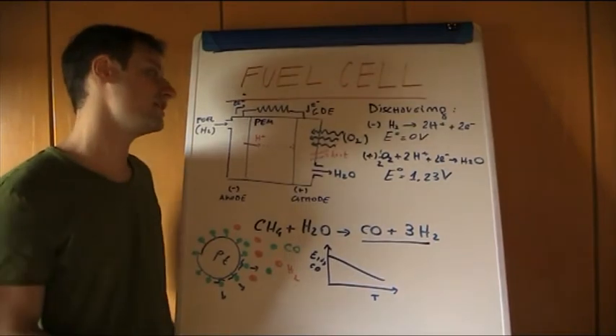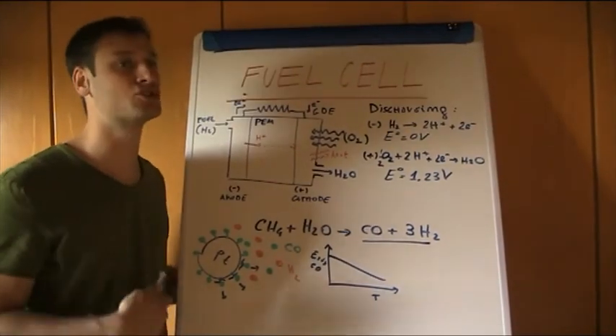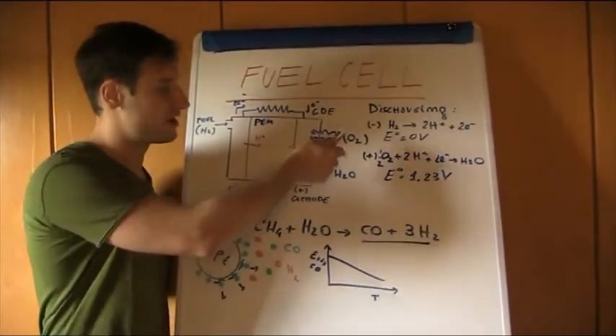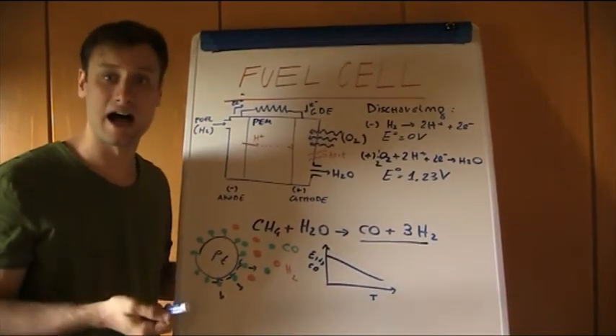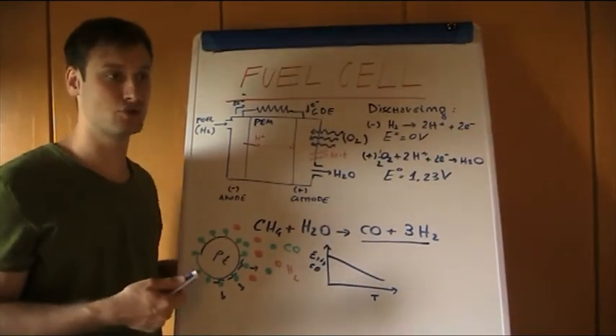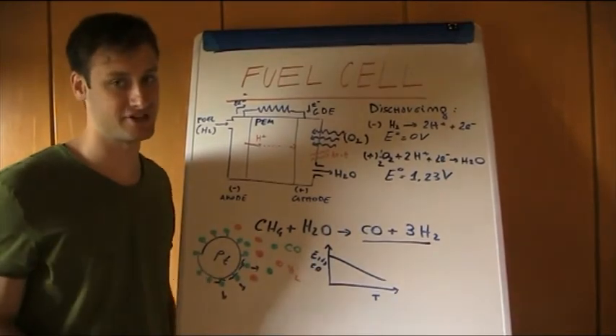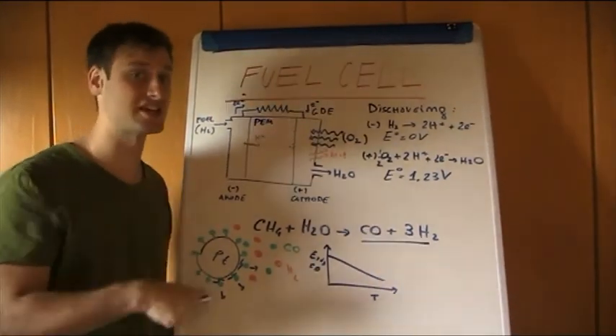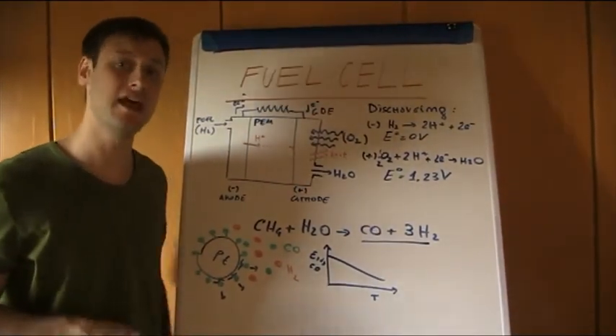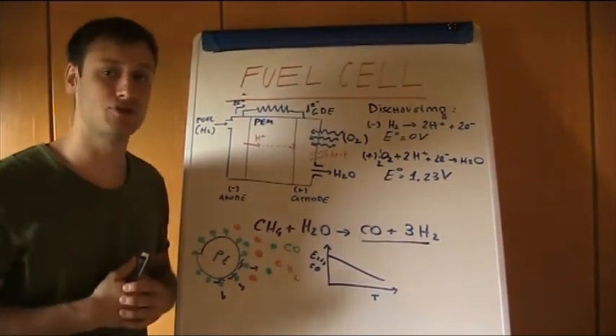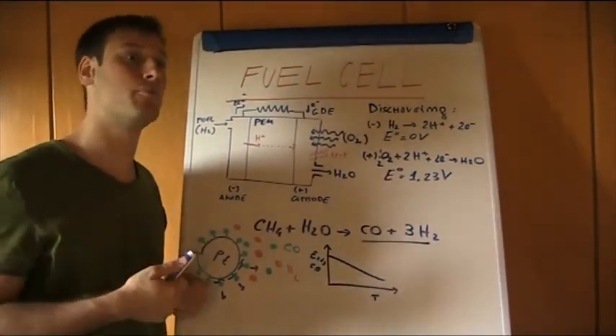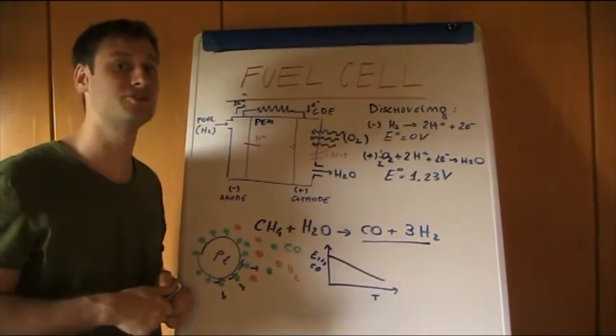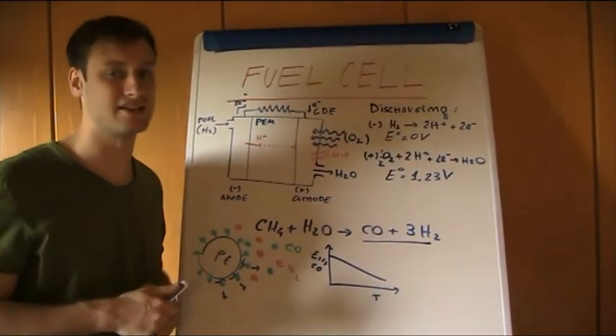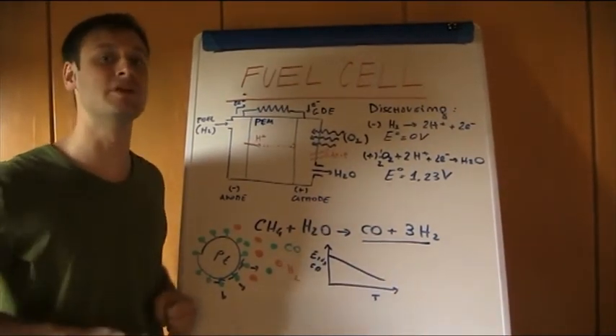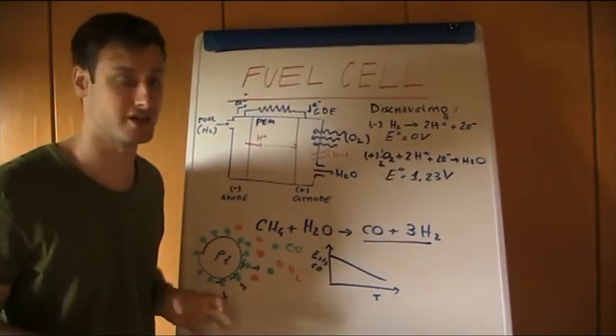And since carbon dioxide is also taken from the atmosphere, sometimes it could be interesting to use ruthenium, but obviously the advantages are not so important if CO2 is taken from the atmosphere, given these extremely expensive materials. But maybe we will see this aspect in the direct methanol fuel cell, when the carbon dioxide is directly the product of the reactions, and so is extremely close to the catalyst. In that case, the use of ruthenium could be a solution in order to avoid the poisoning.